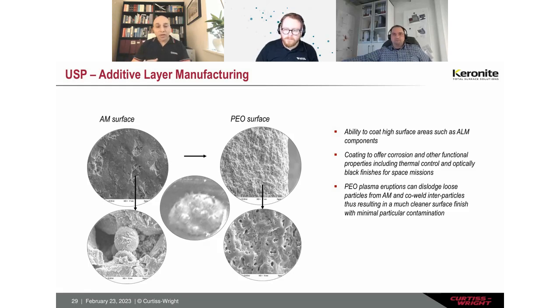Maybe you have to use other technology. Maybe you have to machine it first. Maybe remove those loose particles first by electrochemical cleaning or a polishing technique. But what is shown there is the PEO process on its own. It can clean the surface. It can polish the surface. It can create a uniform coating with uniform coverage. So it's bound to improve the fatigue performance of additive manufacturing components, definitely not reduce it.